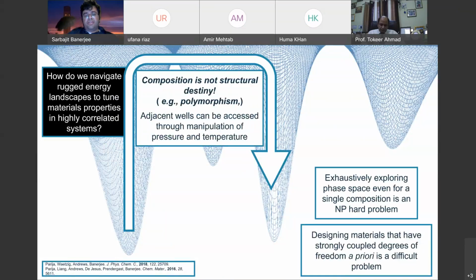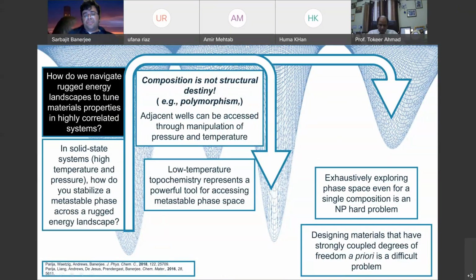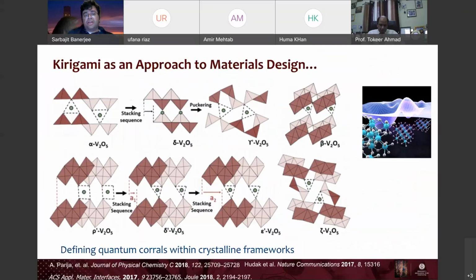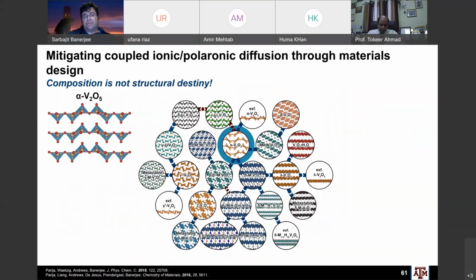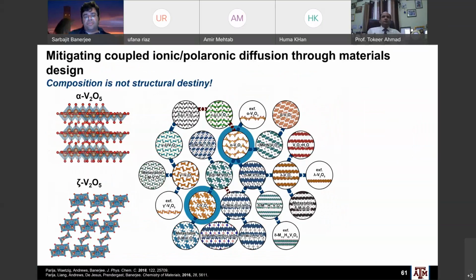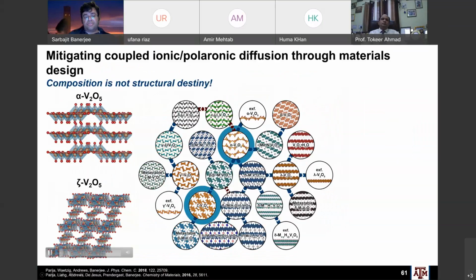Can you identify not just this most stable well, which is the structure of alpha V2O5 I've been telling you about, but entirely different morphologies, right? And so we use this idea of materials kirigami, where we can make these ternary vanadium oxides, and we can etch out the ions, or topochemically de-intercalate the ions to be more formal, to get metastable frameworks, and then we can use those as cathodes, right? And this is an example of alpha V2O5. This is our conventional structure right here, but we also have other structures that I'm going to spend some time talking about, especially this tunnel structure.